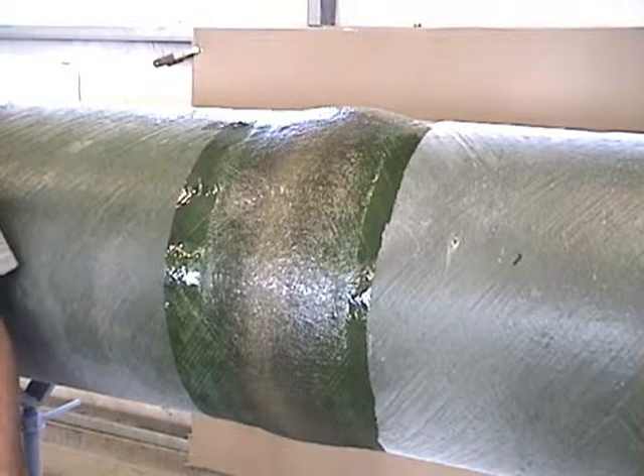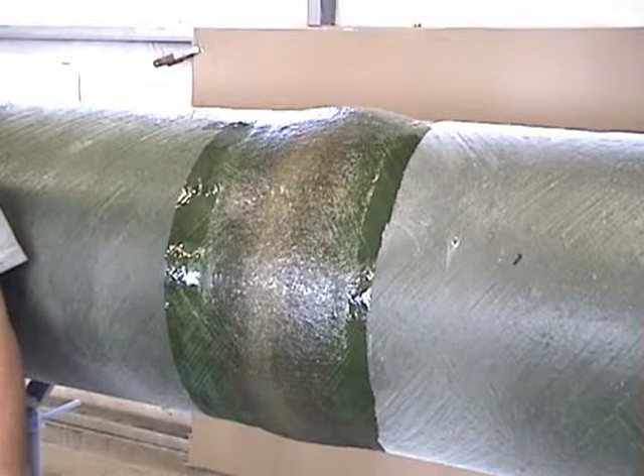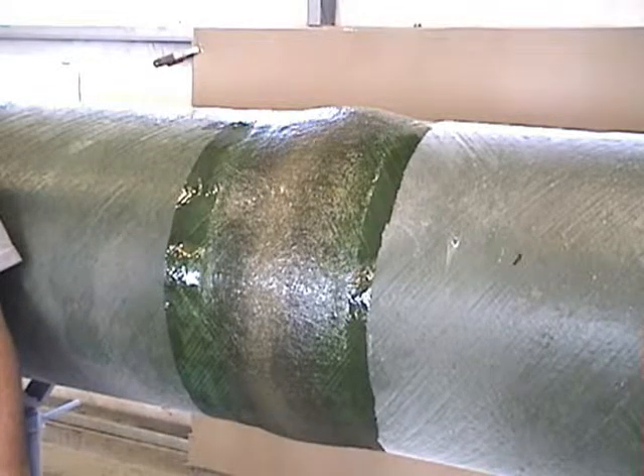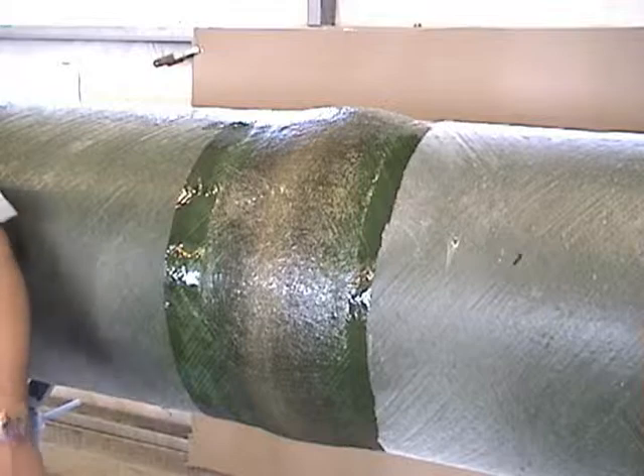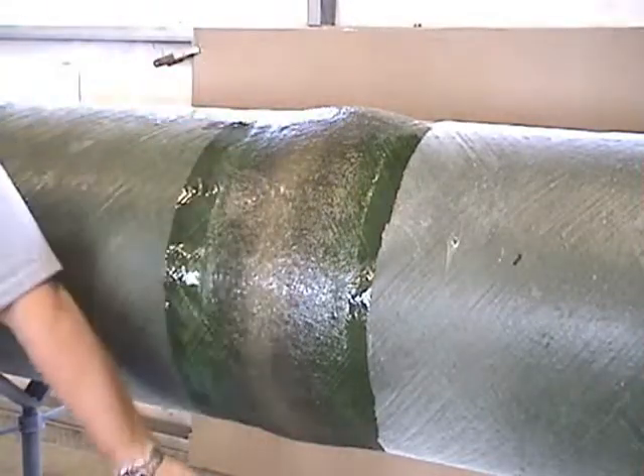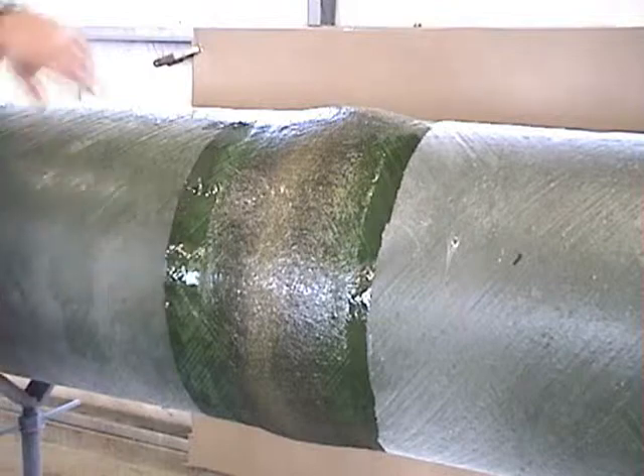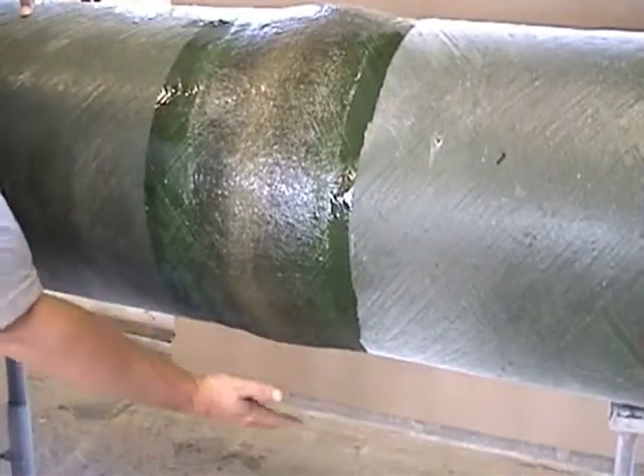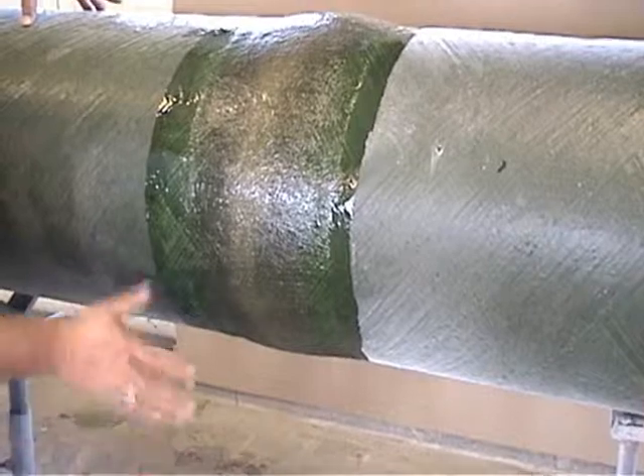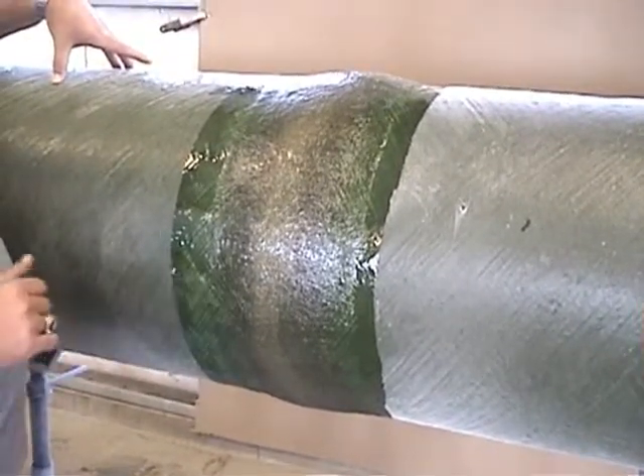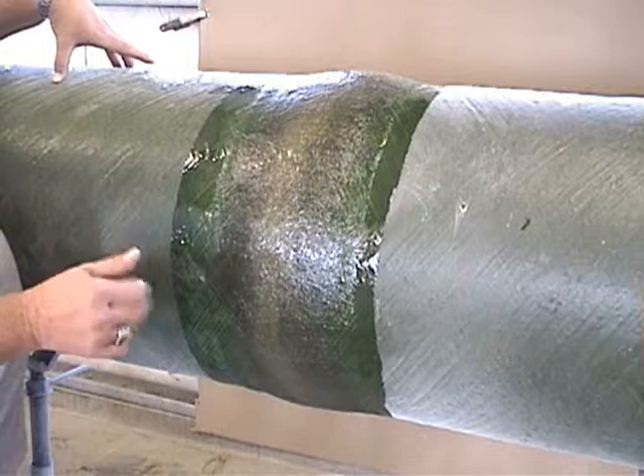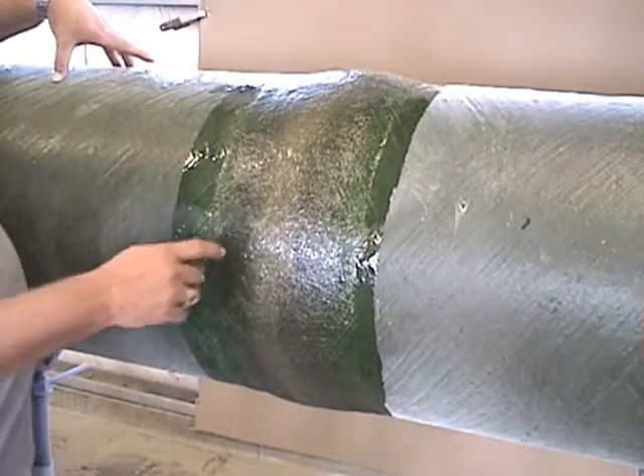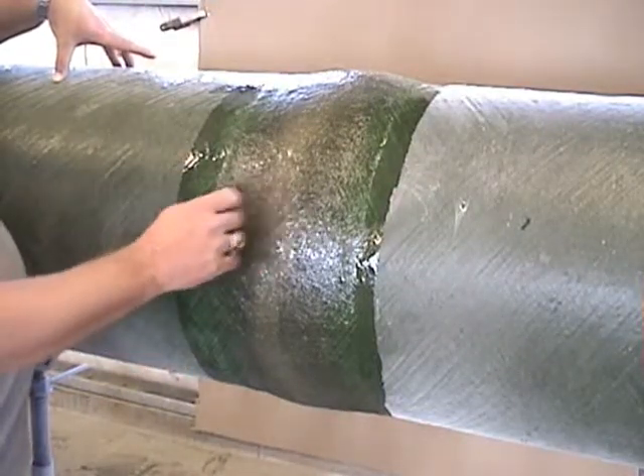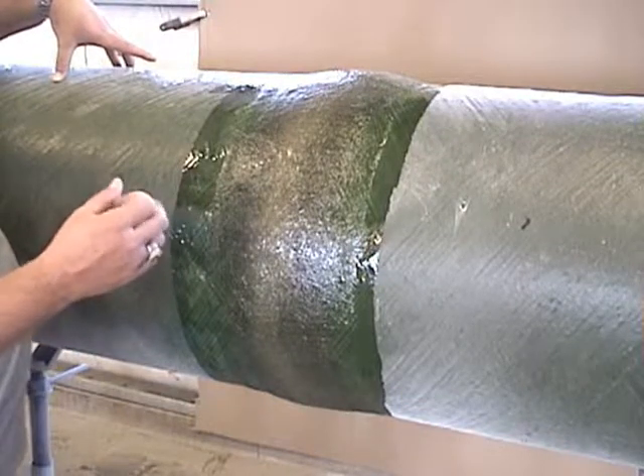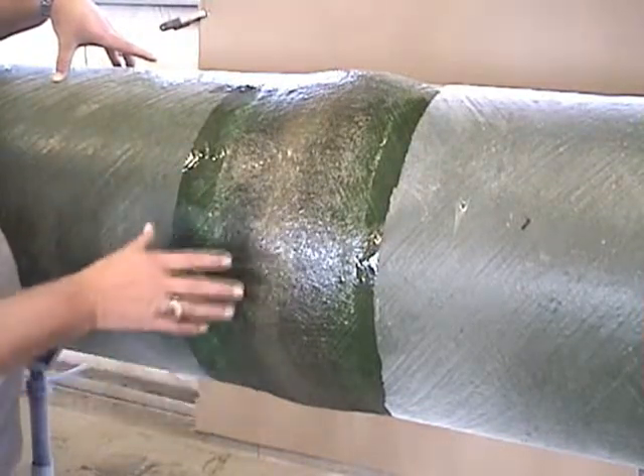When the butt wrap is completed, don't go off and leave it. As it starts generating heat, the resin tends to get thin and run down to the bottom of the pipe from both sides, and if too much resin accumulates on the bottom of this layup, it will sag, creating a bulge at the bottom. So you need to stay with it, rolling the resins back up to the top if necessary, until it gets to the B stage. You'll test when it's at that stage by seeing when it has a rubbery feeling to the touch and doesn't leave any resin on your finger. At that point, you can walk off and leave it.